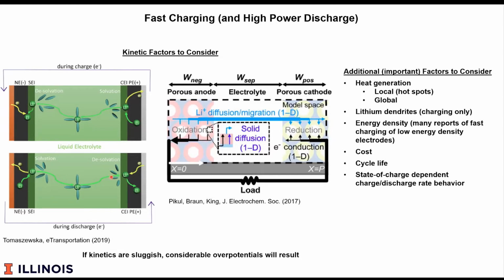Now some of the rate limiting steps include desolvation at the cathode, and then some of the same factors of both ion diffusion and electron diffusion. The fundamental difference is that during fast charging, lithium may plate, it may form a dendrite, and that dendrite could short out the cell. Under a high-powered discharge, there's no danger of dendrite occurring.